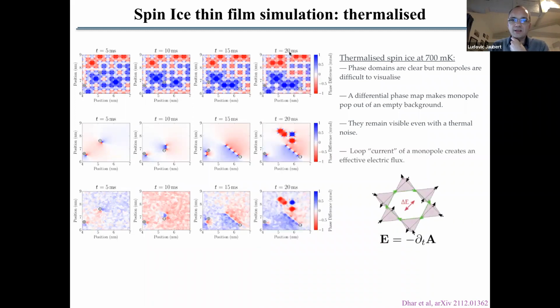And indeed, if we look at time t equal 20 milliseconds, between 15 and 20 milliseconds, there were some pairs of monopoles created, hopping around and closing on themselves. And as you do that, locally, you create a jump of the phase map. And this jump of the phase map, this discontinuity, corresponds to fluctuations of this effective electric field that we were talking about before. So here in this case, it's an effective electric field.